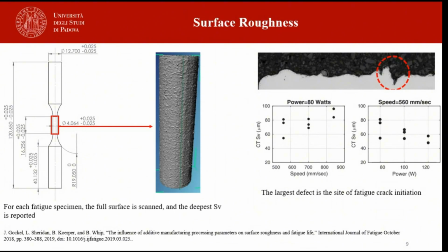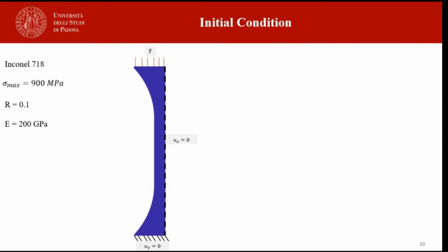For scanning the surface, they used computed tomography for each specimen. The full surface of the gauge section is scanned and the deepest value of surface valley is reported. In fracture mechanics, it is assumed that the largest defect is the site of crack initiation. For simulation, we create the initial model as described in the article. The article states that maximum stress is 900 megapascal. Material is Inconel 718. Stress ratio is 0.1.